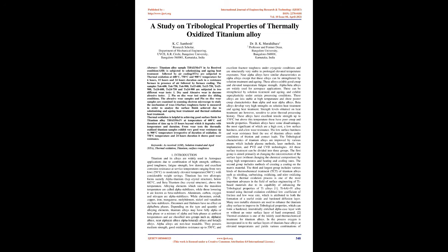The abrasive wear samples and pin-on-disc wear samples are examined in scanning electron microscope to study the mechanism of wear. 3. Surface roughness factor is measured in order to analyze the surface finish achieved due to solutionizing and aging heat treatment and thermal oxidation heat treatment. Thermal oxidation is helpful in achieving good surface finish for titanium alloy Ti8Al1Mo1V at temperature of 600 degrees Celsius and duration of time up to 15 hours, beyond which it degrades with temperature and duration.